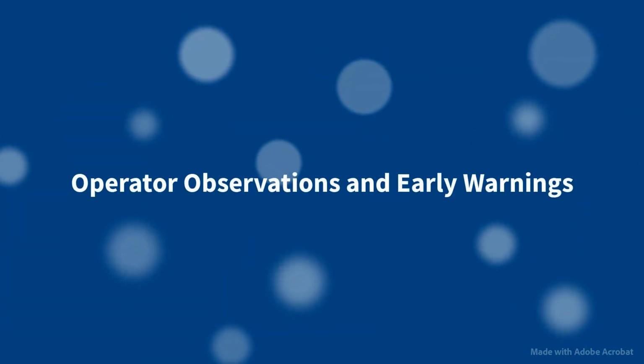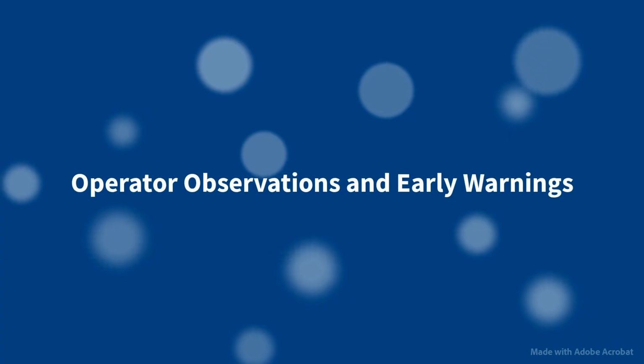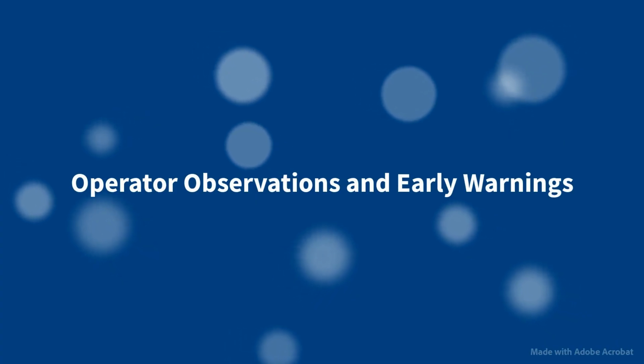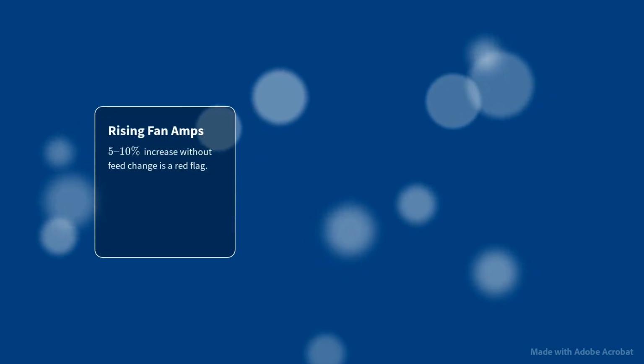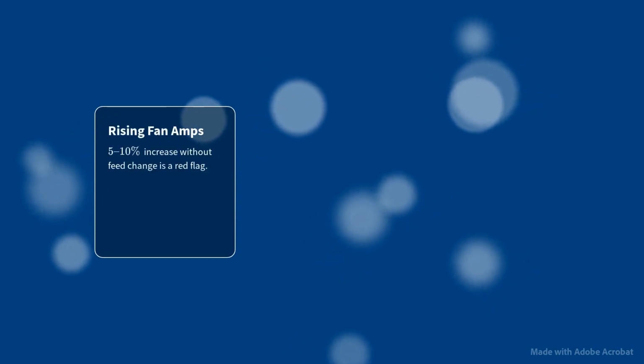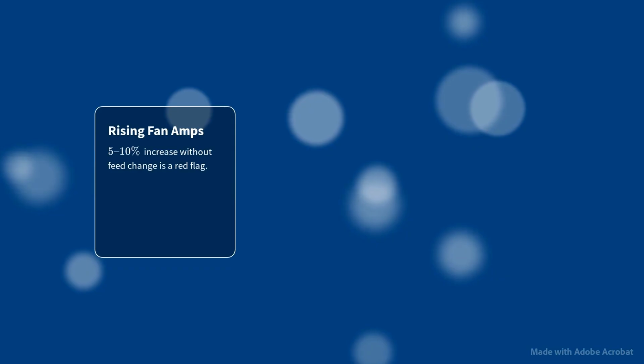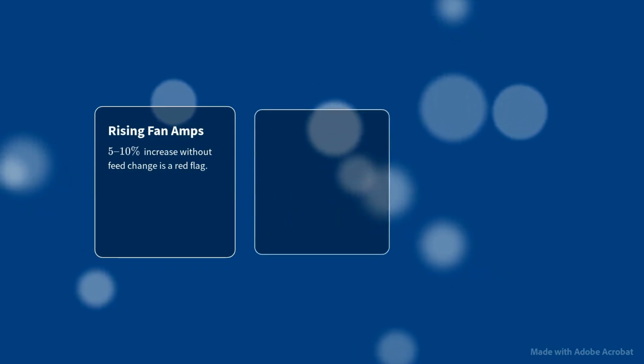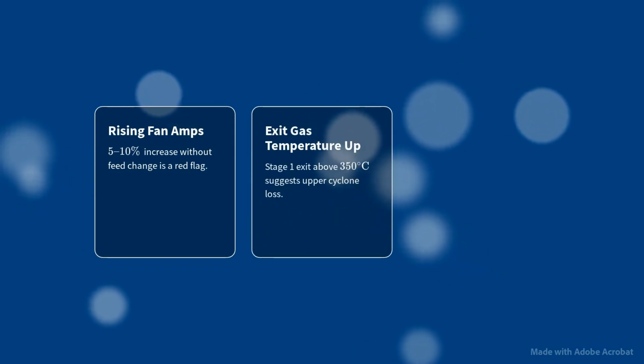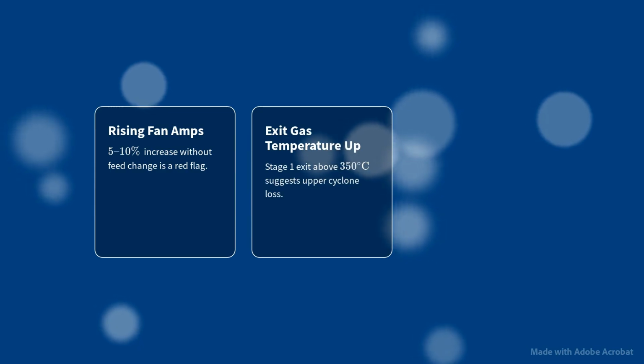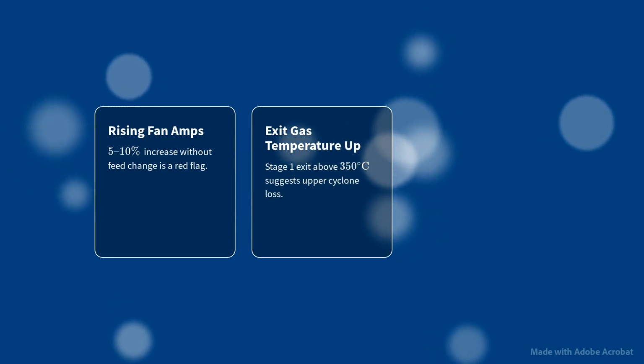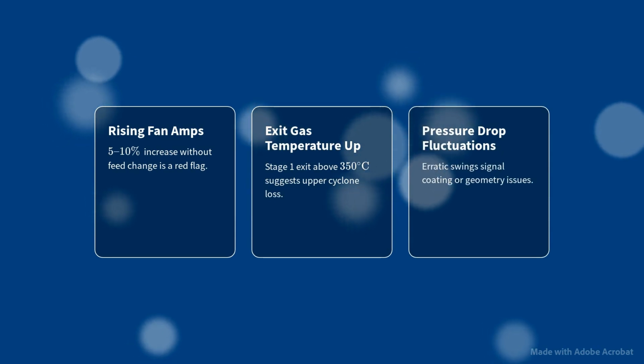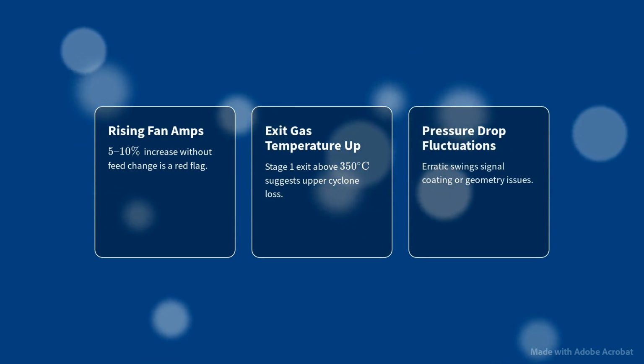Operators can spot early warning signs if they know what to look for. Here are some key indicators of internal cyclone problems. Rising fan amps, especially a 5 to 10% increase without any change in kiln feed, is a clear warning sign. An exit gas temperature above 350 degrees Celsius at stage 1 often points to cyclone separation loss in the upper stages. Pressure drop fluctuations with erratic swings usually signal coating buildup or internal geometry problems.